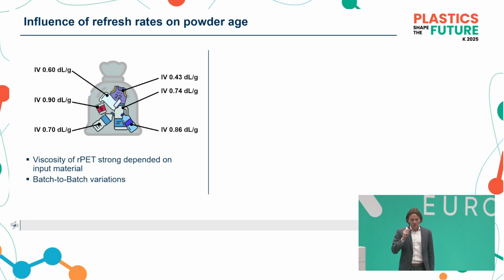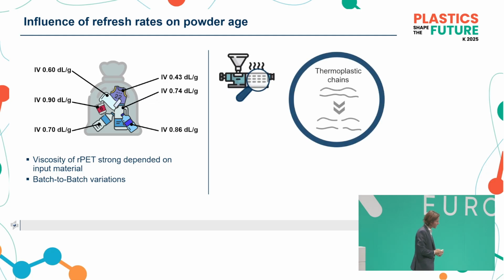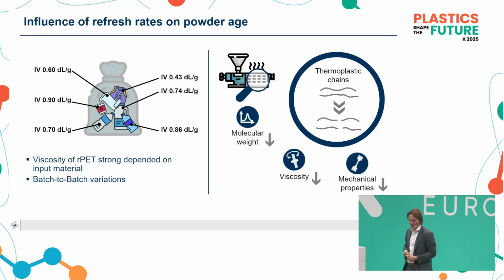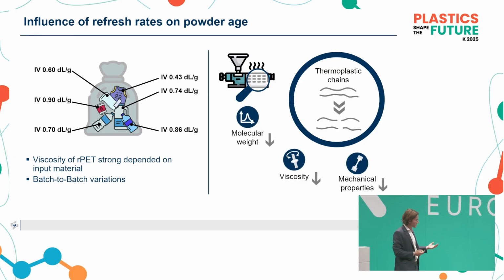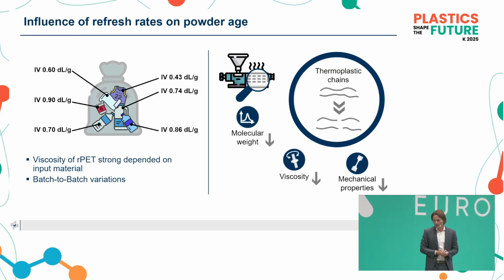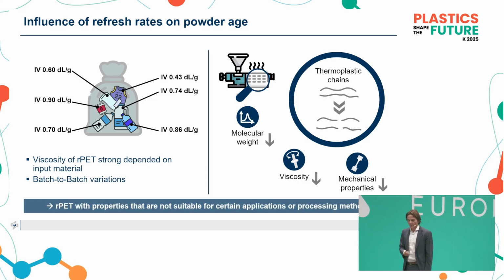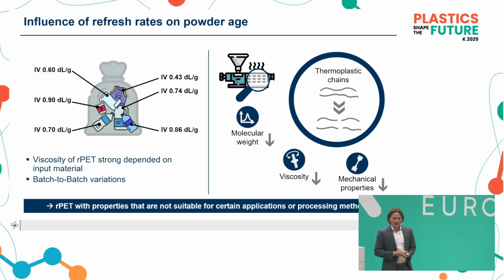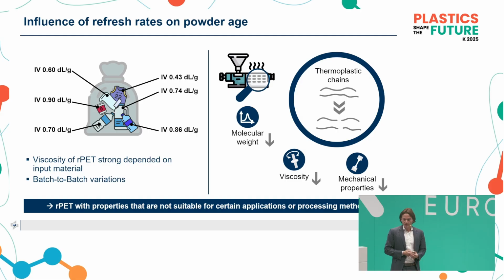In the end, you would always like to have a constant quality again. So you have different mixtures, but whatever you do, you have to prepare a recipe which gives you constant quality. So how can you do that? Often when processing materials to break down the chains, you reduce molecular weight, the viscosity and the mechanical properties, but you can increase the properties again via using chain extenders like Joncryl. And that's what we are doing here in our project.